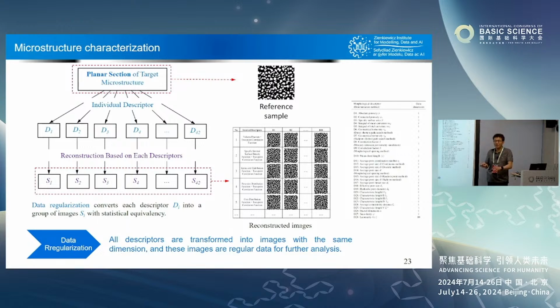So the logic here is that we synthesize an image from the reference, with one guide, using that descriptor individually to minimize the difference between the original one and the measure of that one descriptor. We end up with a set of results. The results only contain partial information of the original image, and that part is captured by that chosen descriptor.